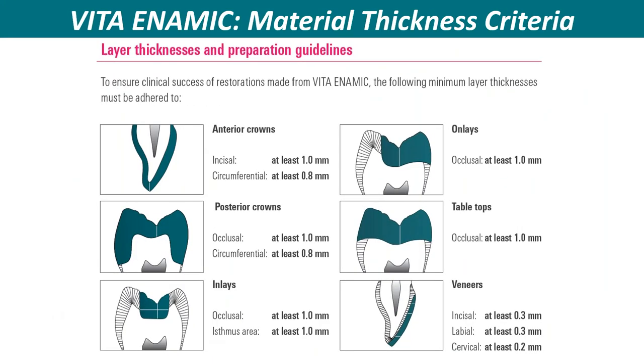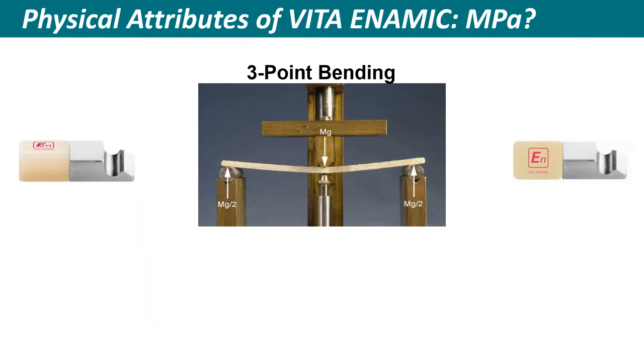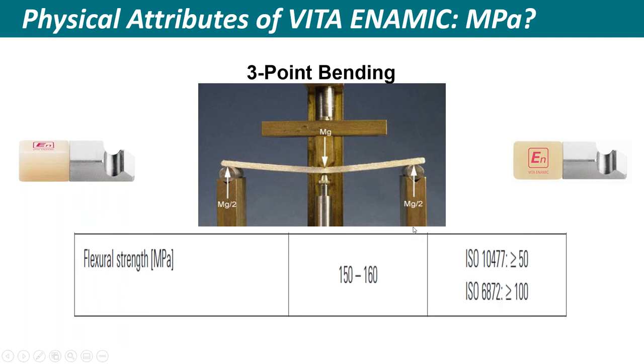We have very thin cross sections with this enamic material because it can be milled so fine. And just to go back to the point of the fracture load versus the static load of the ISO standard material, this is the design that's used for ISO standards. This is a three-point bending test. It's just a bar. It's loaded till it fractures. For enamic, for those of you who are asking how strong is it? In this test standard only, it is 150 to 160 megapascals.